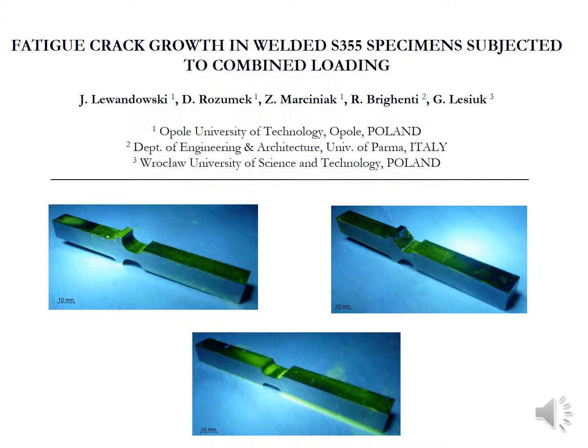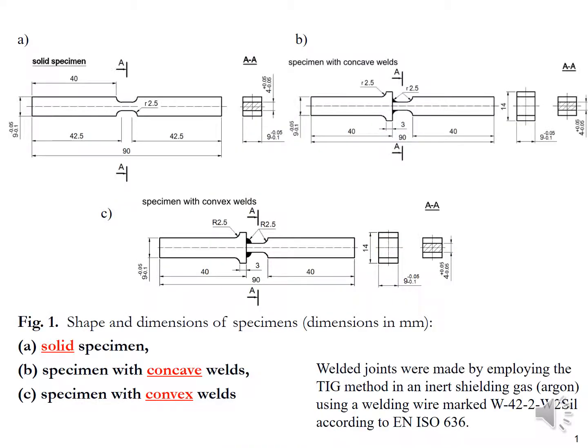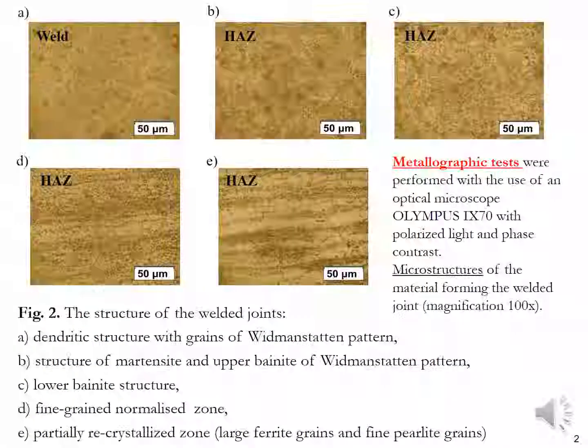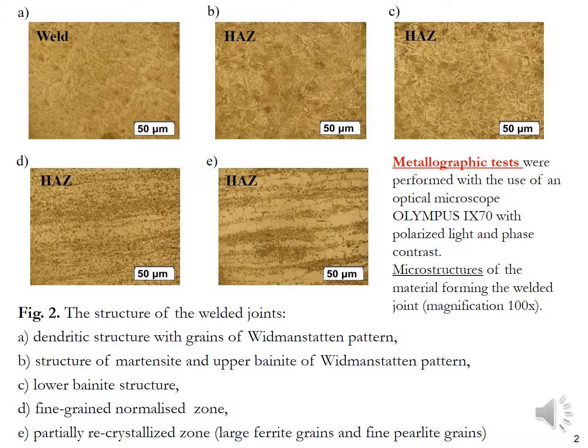This research deals with the experimental study of the fatigue behavior of welded specimens made of structural steel S355 under combined-phase constant amplitude cyclic bending and torsion loading. Three types of weld geometry have been considered: solid specimen without welding, specimen with concave shape welds, and specimen with convex shape welds. Metallographic analysis has been performed on the specimens, analyzing the welded area and the heat affected zone close to the weld.